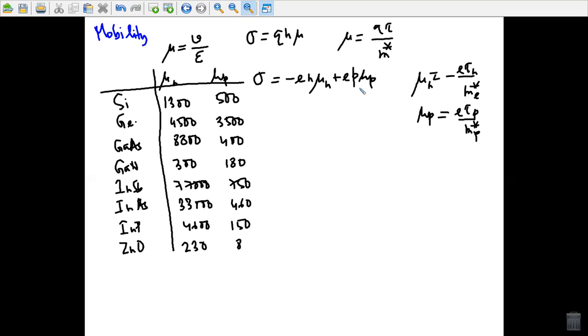In the relaxation time approximation, these are given by mu n equals minus e τn divided by m n star, and mu p equals e τp divided by m p star. As a unit, usually centimeter square per volt second is used, while copper at room temperature has a mobility of 35 centimeter square per volt second. Semiconductors can have much higher values. In two-dimensional electron gases, the mobility can reach several 10 to the power 7 centimeter square per volt second at low temperature.